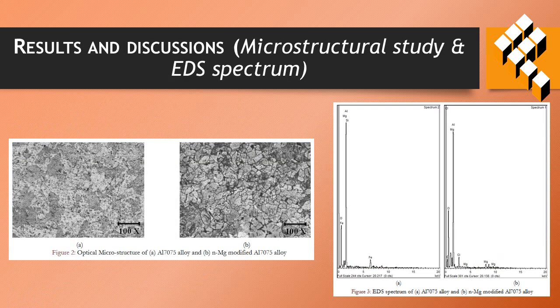Figure 2 shows the optical microstructure of the base alloy and nano-sized magnesium modified alloy. From the outcome, it can be observed that uniform distribution of particulates takes place. Figure 3 shows the EDS spectrum of base alloy and nano-sized magnesium modified alloy. From the outcome, it can be observed that more magnesium element was found by the EDS spectrum.